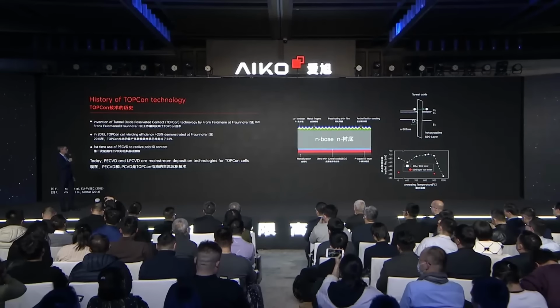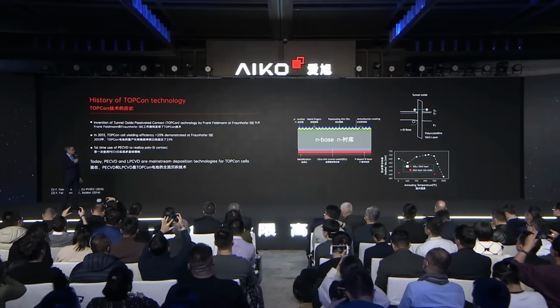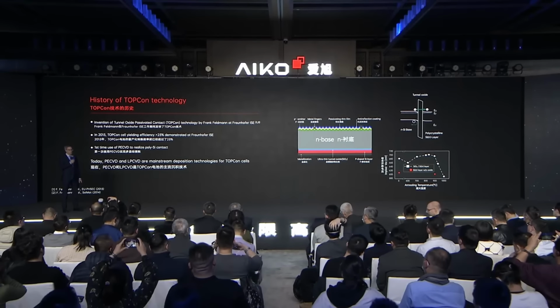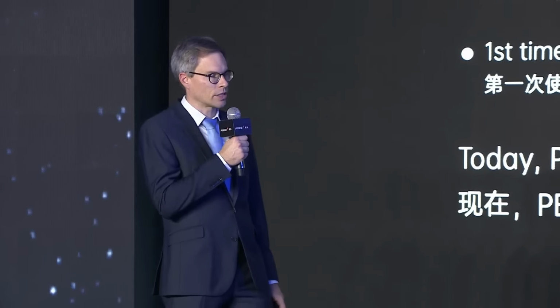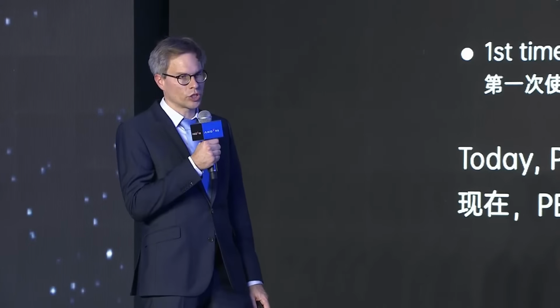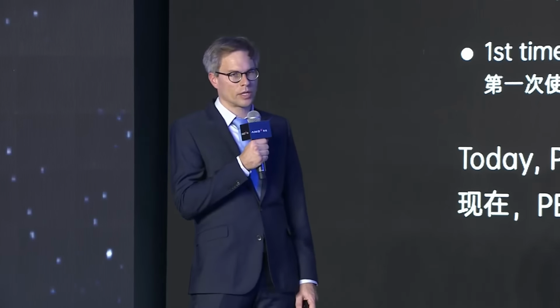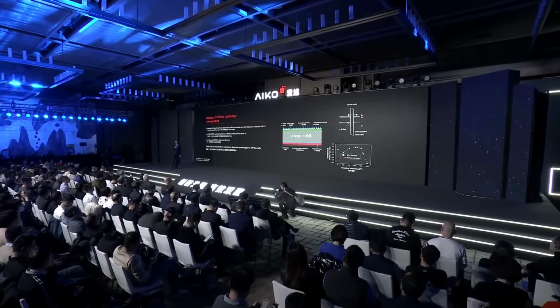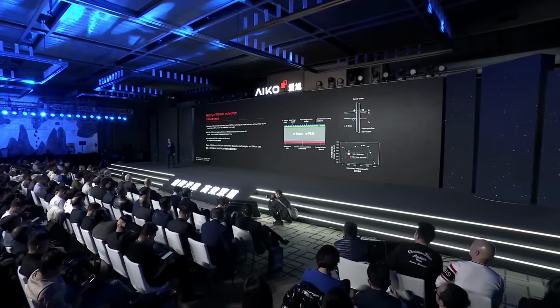Talking about TOPCon, here you can see a sketch of a cell structure. It features a boron-diffused emitter at the front side, which is well passivated with aluminum oxide and silicon nitride. At the rear side, recombination is effectively minimized by a stack of a thin tunnel oxide and a heavily doped polysilicon layer. When we did that work at Fraunhofer in 2013, the unique thing about this technology was that we could actually show an efficiency benefit when using passivating contacts. The first cells had an efficiency of more than 23%. What was also unique is that we used, for the first time, the PECVD deposition technology to create the polysilicon contact on the rear side.